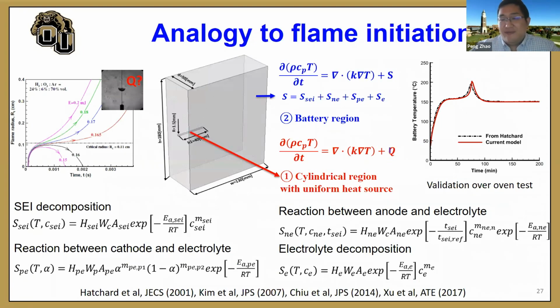Okay, the next question from Zhao. How is the source term of chemistry considered in your modeling, especially around the cathode? Which reactions most correspond to the heat release? So for the source term, we basically use a very simple source term. It is a constant source term that lasts for a certain duration, a few seconds. And we use very fine grids to resolve the interface, because that's the part where you might have the highest temperature and the triggering reactions.